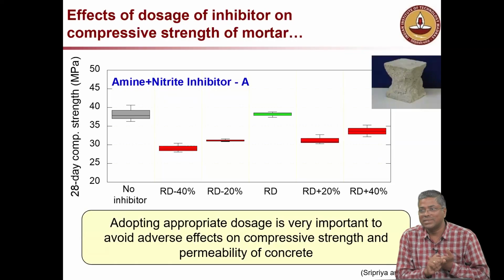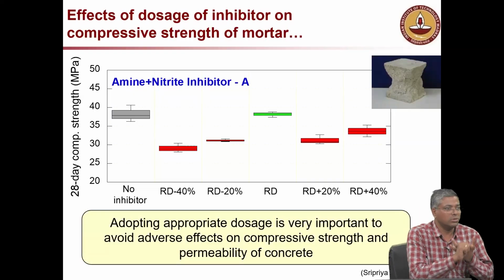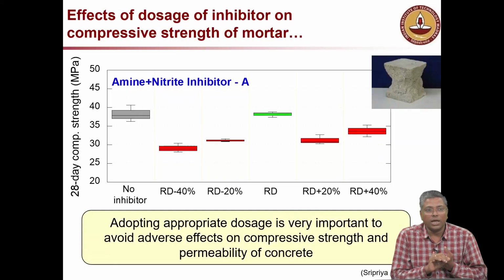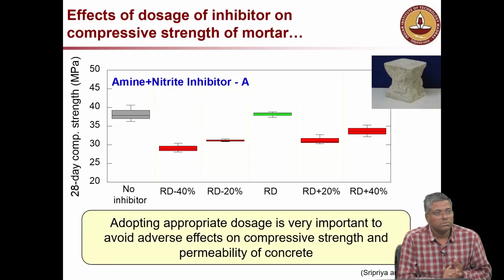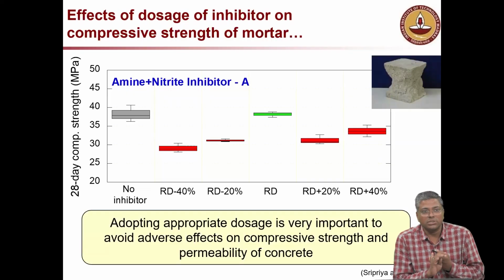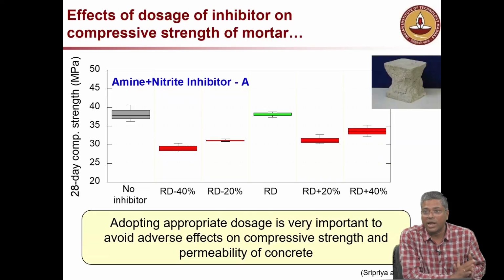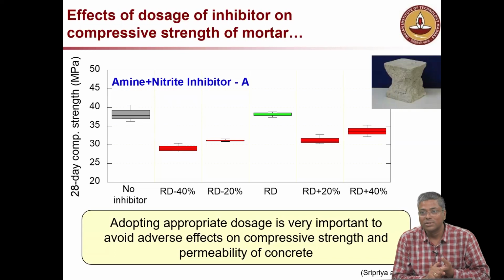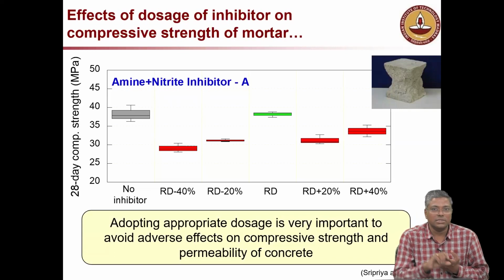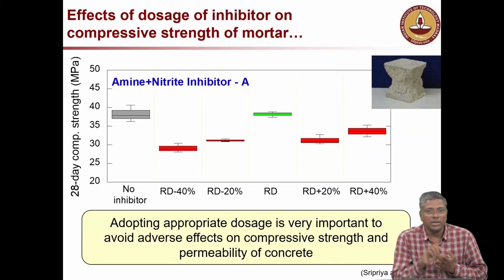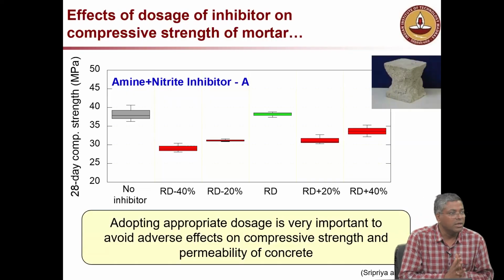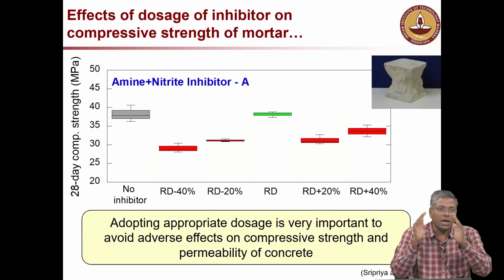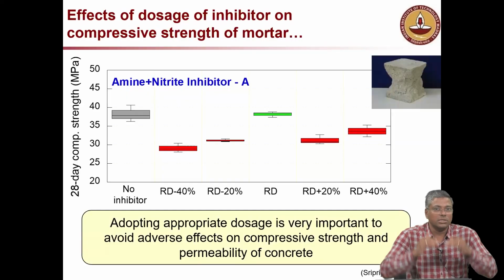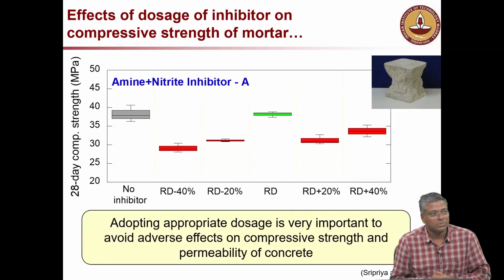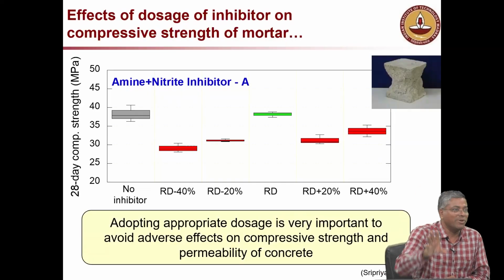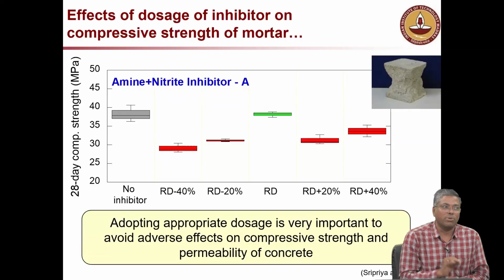Usually when corrosion products are marketed, or corrosion resistant or corrosion enhancing products are marketed, they talk only about corrosion. But does it make sense to test the concrete with that chemical if you are actually mixing that chemical to the concrete? So what you see here is the green box over there is the recommended dosage for a particular inhibitor. The red ones are when you deviate from that recommended dosage, the compressive strength of concrete dropped. This test I did 3 times just to confirm. So dosage is very important.